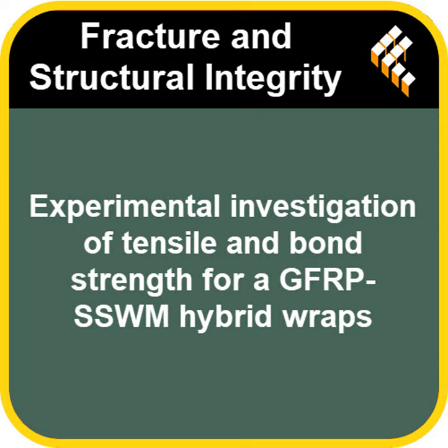And what about ductility? You mentioned SSWM brings ductility. How did that play out? That's the other side of the coin. Ductility is how much it stretches or bends before it snaps. Right. You don't always want brittle. Exactly. The pure GFRP samples, GG and GGG, were strong, but they failed abruptly. Brittle failure, lower rupture strain. Okay. The SSWM only samples were much more ductile. They absorbed a lot more energy before failing.